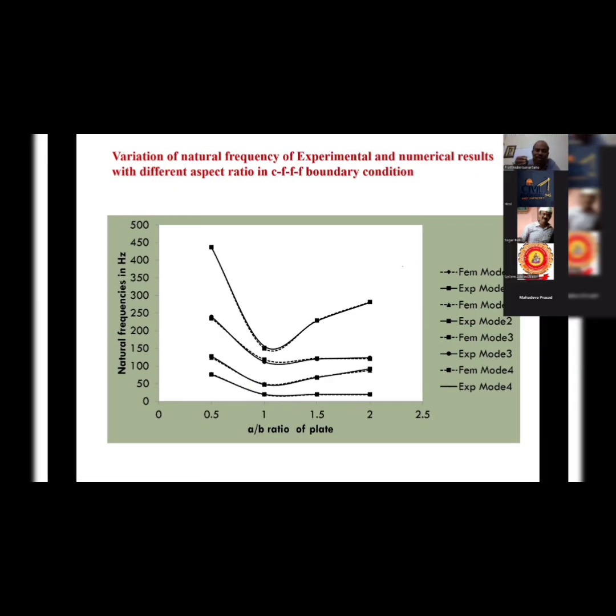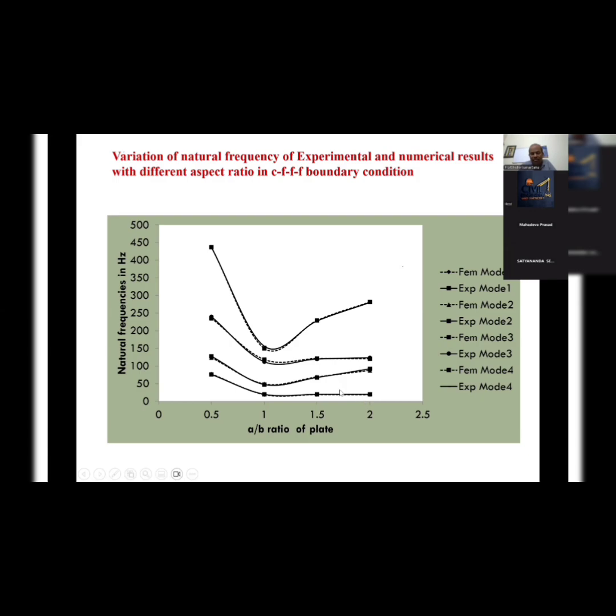Similarly, aspect ratio. Aspect ratio means length by breadth of the plate. When it is a square plate, it is 1, or else it is 0.5. If you increase the length, then the ratio is 1.5, 2. This is the first frequency, second frequency, third frequency, fourth frequency. With experiment and numerical, as you can see, with increase of the aspect ratio the frequency increases in this case, but decreases in the first frequency. So all these things have to be studied for composite to composite.